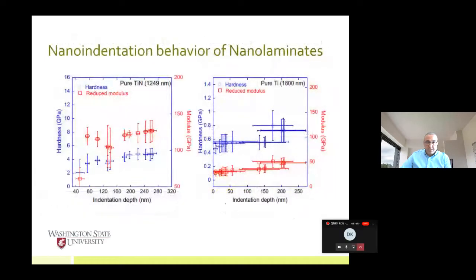If you look at the mechanical properties of these nanolaminates, here what I show you is pure titanium nitride that was about 1300 nanometers and pure titanium. Reasonable hardnesses were achieved, and as you can see, the titanium nitride tends to be about 8 gigapascals or so if you go for the reduced modulus. The combination of these would obviously depend on where you measure the hardness, but this was good to know that we are able to produce the nanolaminates by the sputtering techniques, but we have hardnesses which are comparable to at least the bulk materials, and that is also representative of if there are any defects.